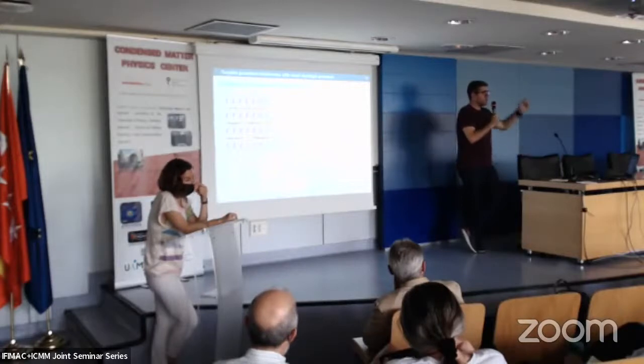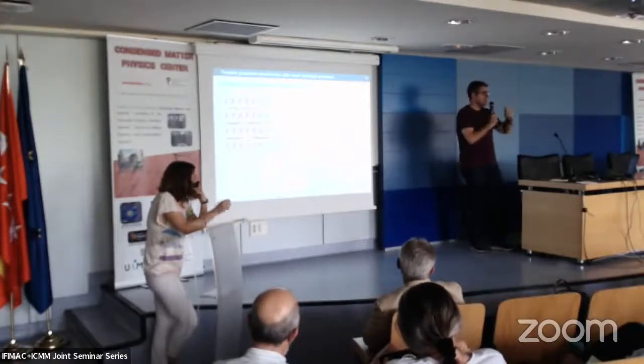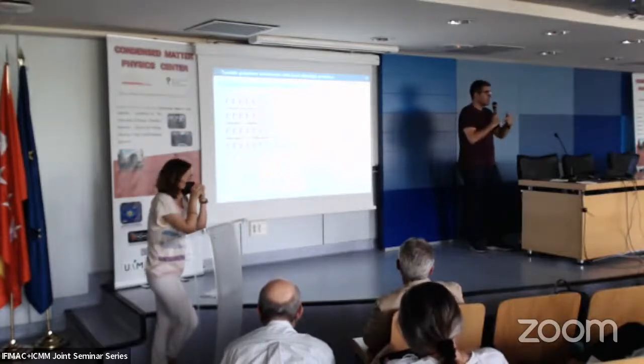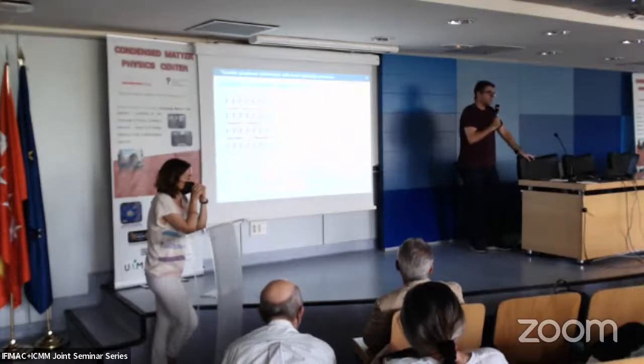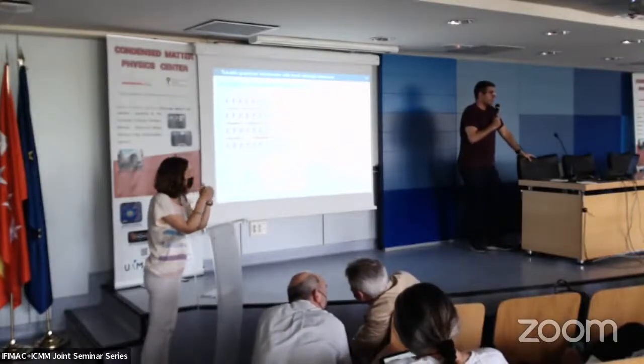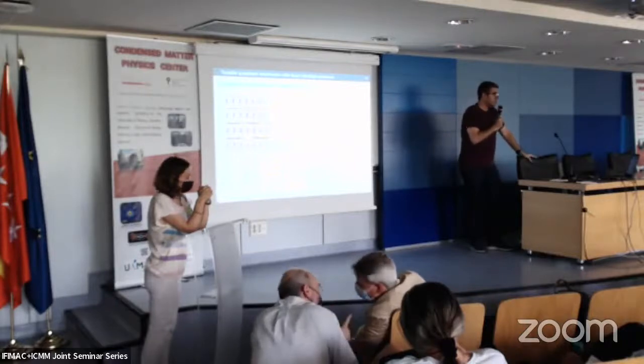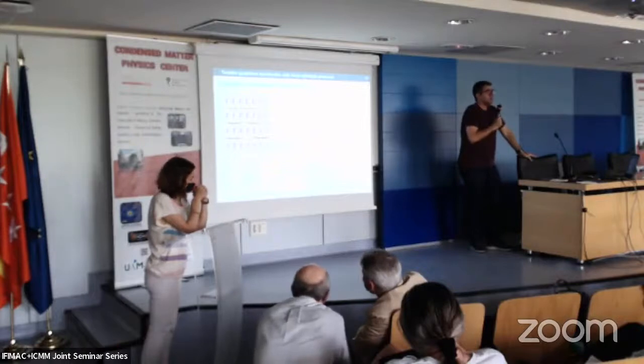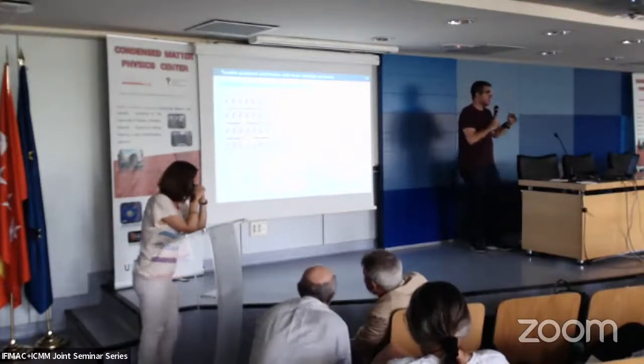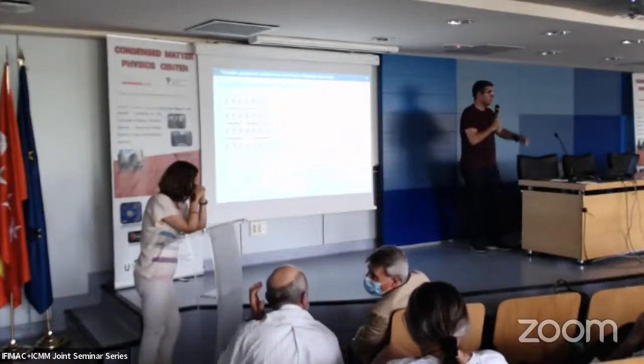This could be okay. But then they also do some transport measurements as a function of load, and they say that at some point it stops conducting, or rather conducts less, but then it goes on. And this is quite arguable because there is an effect of the tip with the load you're applying that is changing your conductivity. So that part is not so clear. But in any case, they said that they only achieve that in bilayer graphene. We were expecting that if I have few layers, I push, and at least some of them will bond and give diamond. We tried, I don't remember if we tried bilayer itself, but at that time we tried few layers, of course, and we were able to sink a few nanometers, so it was a really sizable downward displacement, but we didn't find any hint of diamond there.